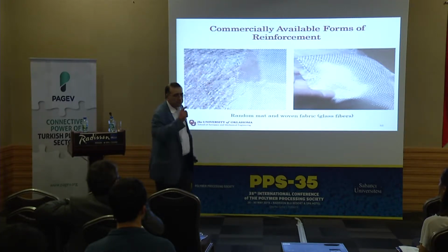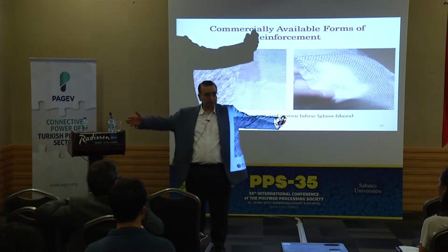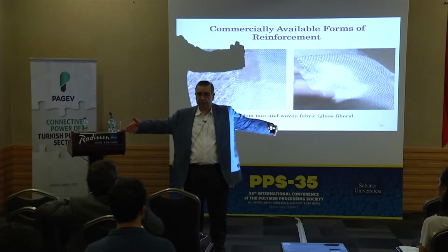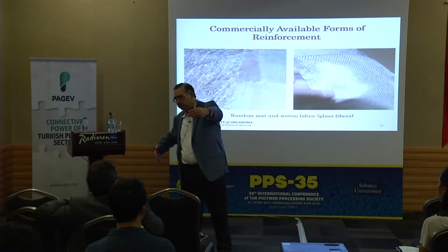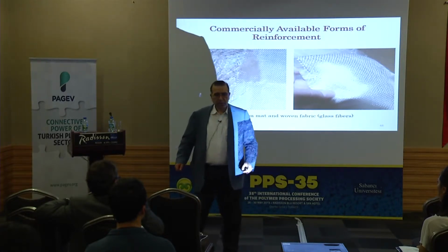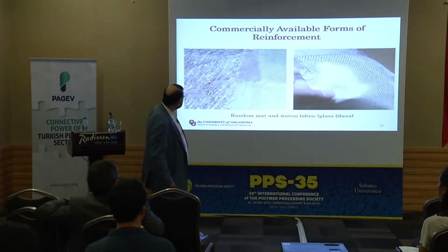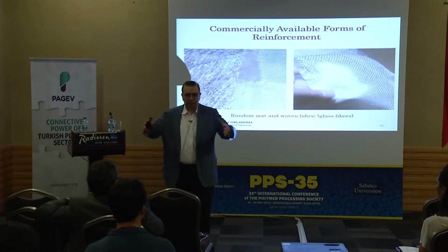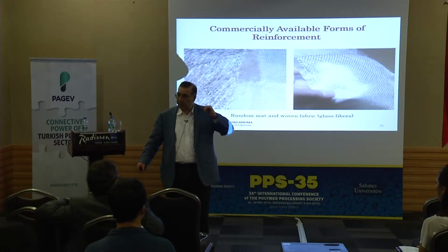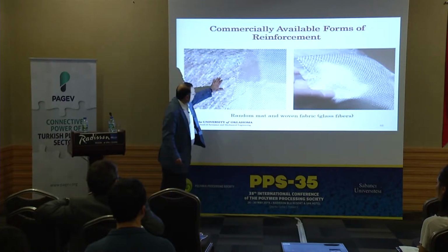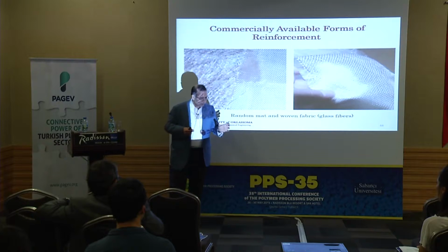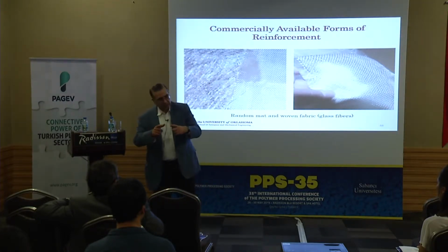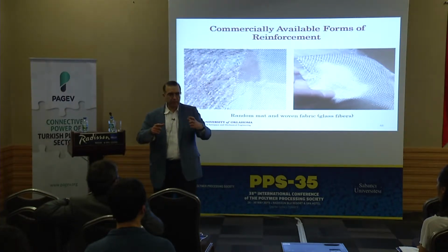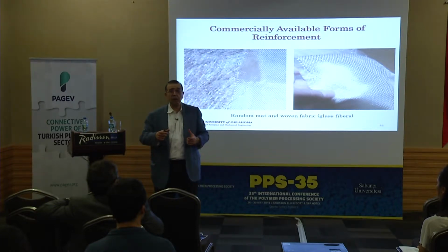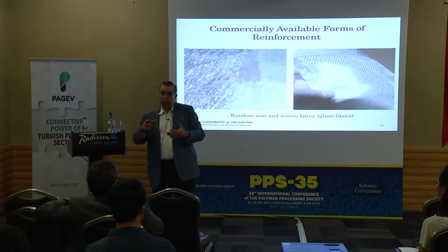The random mat also, if you are processing with random mat, you buy the big roll, and maybe the width of the roll is like 1 meter, and it is like 100 meters or 60 meters long. Because of the nature of the microstructure, you will see some gaps, right? So both at the micro scale and the macro scale, there is some non-uniformity in these random mats. So as you are using the roll that you purchase, at every 10 meters, you need to cut a little part of your fabric or random mat and weigh it and see if there is any variation in the amount of fiber per unit area. And you might have 10–20% variations.